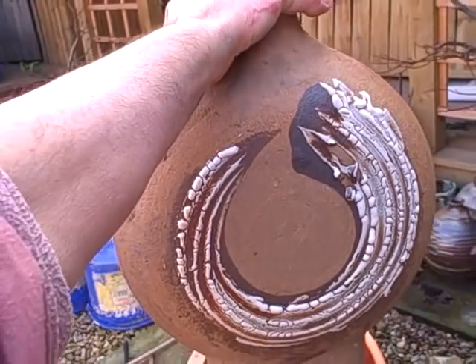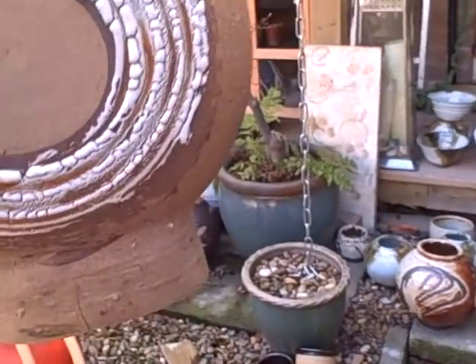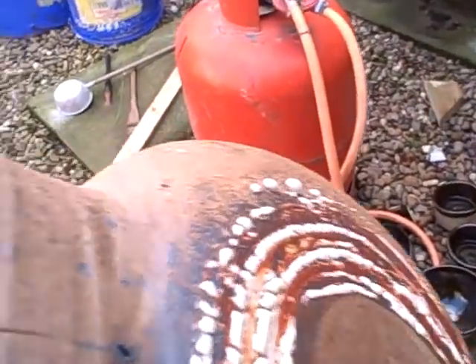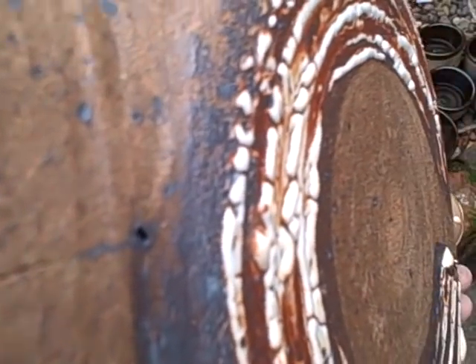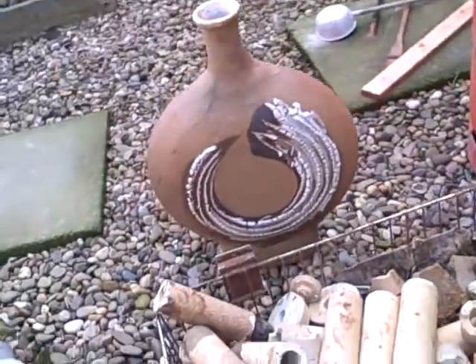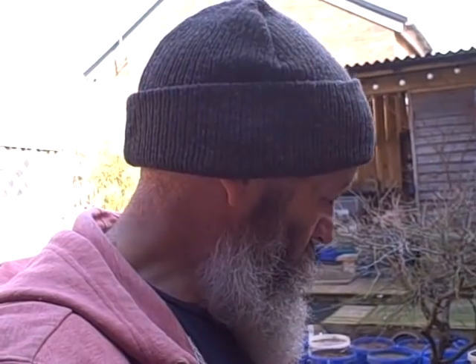One more — one more mistake. This one here — as you can see that's a nice big pot, but it's cracked at the bottom under its own weight. It's quite thin that. You can see it's split both sides, so I need to make these bottoms a bit chunkier. It's quite a nice bottle. That was caused by the weight of the pot and the thinness of the rim — you'll learn a lesson there. It'll make a nice garden pot for the summer.